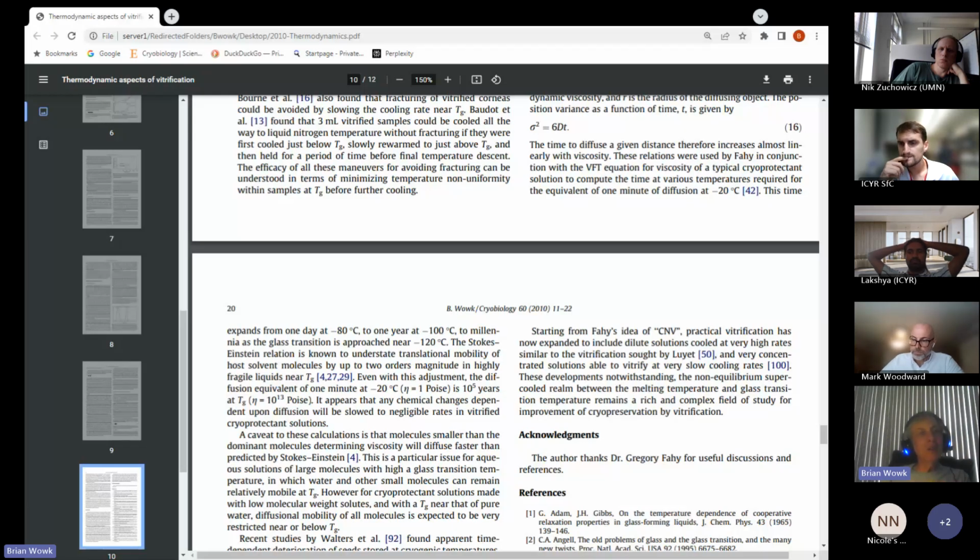So the moral of the story is that the standard theoretical prediction for the ability of chemical reactions to proceed at the low temperatures that vitrified materials are stored at is negligible. The main concern seems to be ice nucleation, which, as we've seen, proceeds much faster. But we don't seem to need to worry much about chemistry below the glass transition temperature.